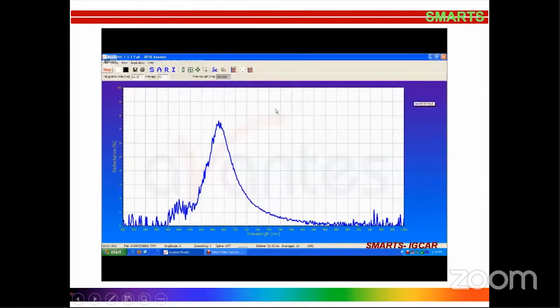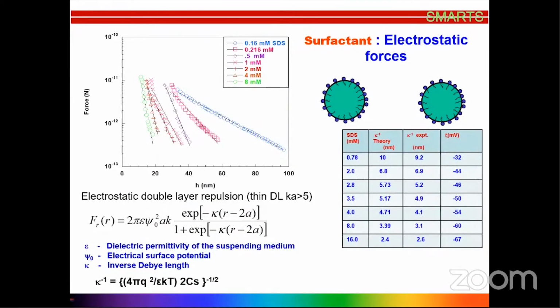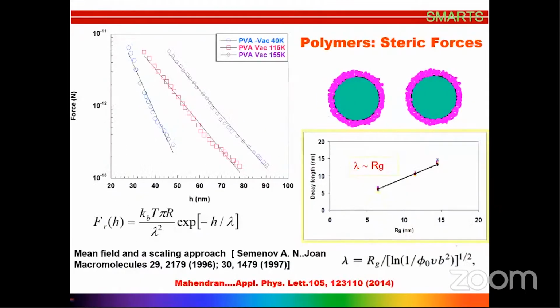And we have used this concept to study the forces between surfactant stabilized systems. We have studied the forces between sterically stabilized systems. Here the beauty is that if you have a polymeric system and the polymer is used to stabilize these particles, the decay length becomes comparable to the radius of gyration of the polymer. That means you will be able to tell the molecular weight or the radius of gyration of the polymer by fitting the experimental force data. So you see here the force is 0.1 piconewton to 10 raised to minus 11 newton. That's the kind of forces acting. And obviously all these things are validated with other experiments and theoretically.